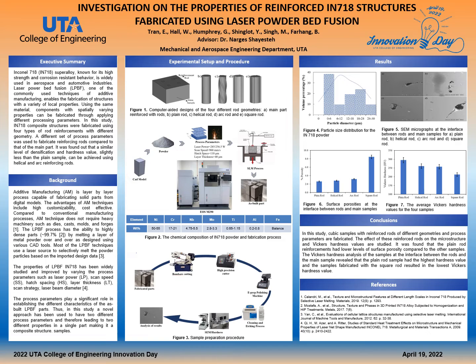Based on the analysis of the results, the plain rod sample had the least amount of surface porosity, 2.6%, among all the samples. And this observation can be expected as the plain sample was fabricated homogeneously without having an interface with any strengthening segment. The samples fabricated with helical and arc rods had a surface porosity of 2.8 and 3.2% respectively. The similar level of surface porosity observed for these samples can be attributed to the similar cross-section of their interface with the main section.